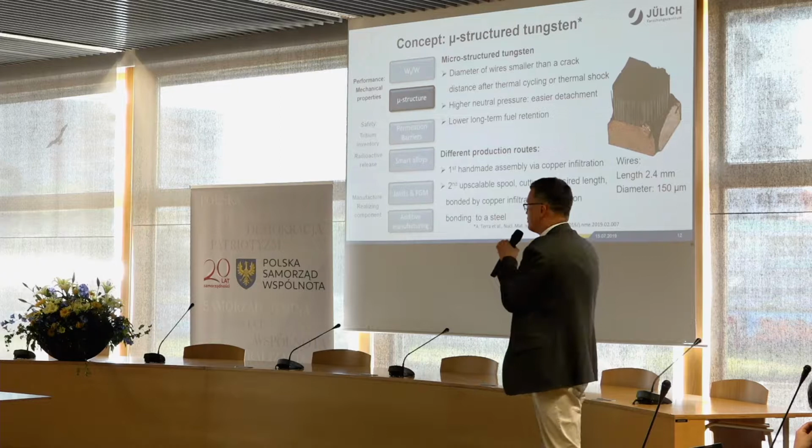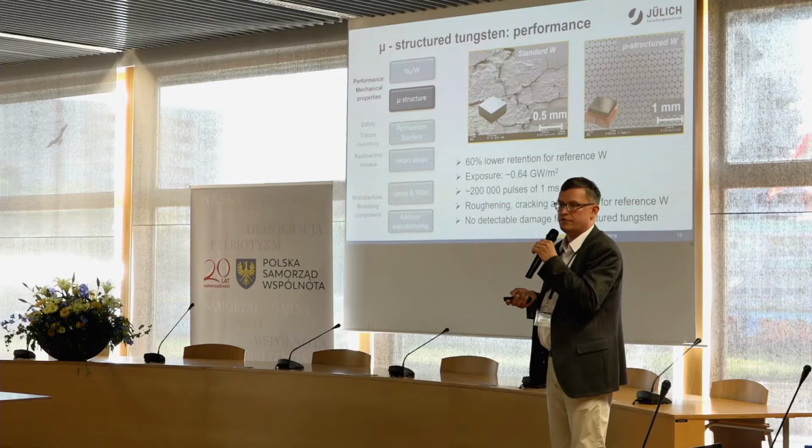And here are actually the most interesting results, I would say. We shot quite a massive load on this tungsten. We put both of these materials under the same condition and shot two lasers with 0.64 gigawatt per square meter. It was 200,000 pulses of 1 millisecond, which was examined on both of these materials.